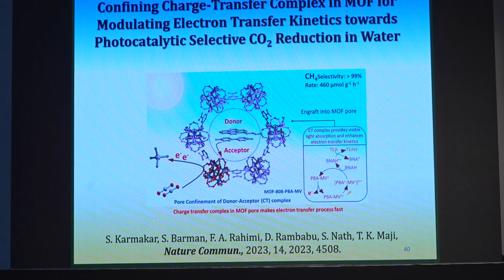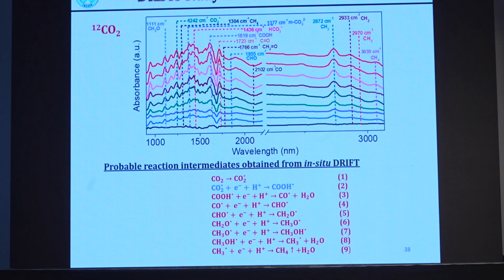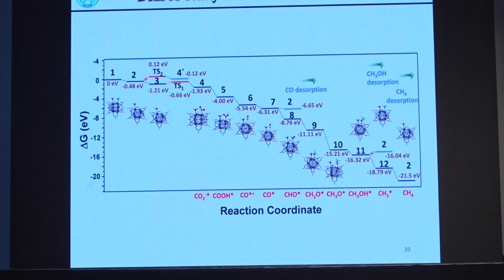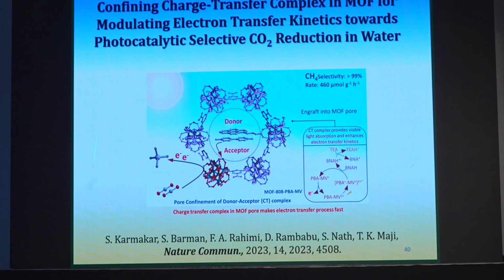Again in situ we have done it. So it is the 8 electron, 8 proton reduction. You have CO2 to CO2 radical, COOH, then CHO, CH2OH, CH3OH, CH4. All these intermediates we can track here, okay? The CH stretching frequency comes around 3000, so that is the CH4. You can see the CO, but the CO intensity is less because it is immediately converting to another product, CHO, and eventually that's why the concentration is less. Then we have done the free energy calculation to further understand this process. So this is the whole concept of how we have done it.